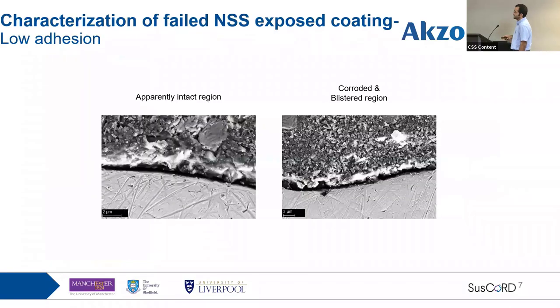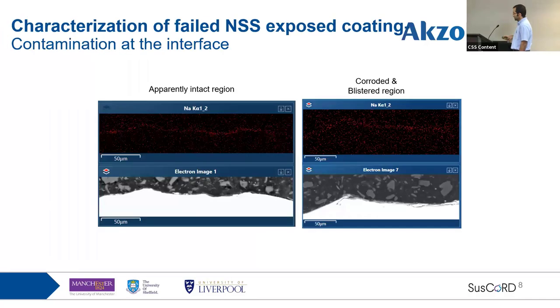So the first thing that I observed, looking at the interface, is that the coating is detached from the substrate on apparently intact regions and also on the corroded regions. And when I did the EDS, I could detect contamination at all these interfaces, which may indicate that this contamination exists everywhere on this surface and has resulted in lower adhesion, but it probably is not the main cause for the failure of these panels.